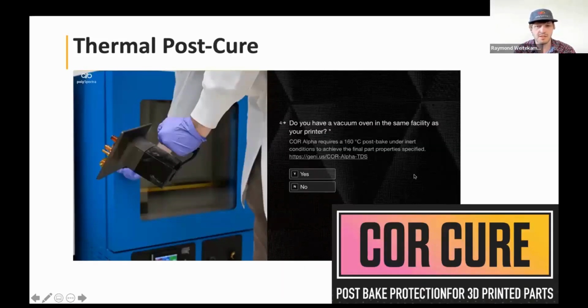Then another thing that you'll see on the website, resin.polyspectra.com, is that because the working temperature of this is so high, depending on how we measured it, as we shared earlier, the TGs are between 165 and 175 C, depending on the way in which you calculate it, it goes through a thermal post-cure. And one thing that I'm very excited to announce today is a way that we're working to make this simpler and lower the burden in terms of the requirements.